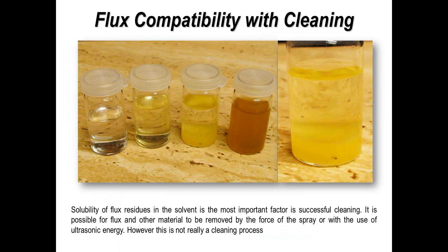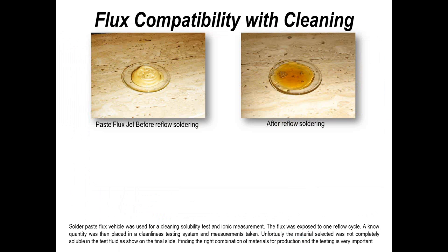In this example, the solids material has separated out to the bottom of the container, which would not generally be considered as fully soluble. Making sure you select a material compatible with your cleaning process and your soldering process is fundamental. It's fair to say that a lot of companies have successfully conformally coated without cleaning, but even those companies, particularly in the automotive industry, have been re-looking at cleaning for certain applications to improve adhesion and long-term reliability of coated products. If you're evaluating a cleaning process, consider simple methods before doing expensive SIR testing and laboratory studies.